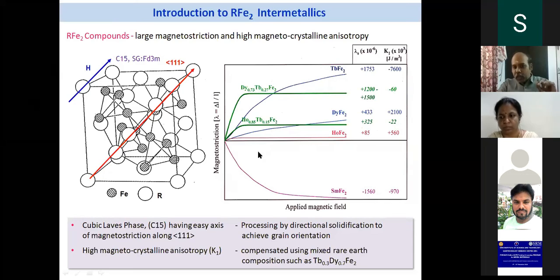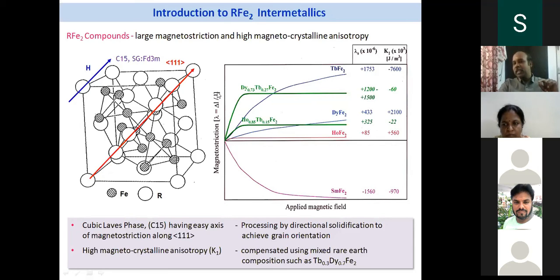TbDyFe2 alloy. If you see, this material is found to saturate at low magnetic field. Although the magnetostriction is low compared to TbFe2, I get a very high magnetostriction at low fields. So this is the advantage of using this material for any practical device. Accordingly, this material, as I told you, was discovered by Naval Ordnance Lab, USA, and it is called Terfenol.